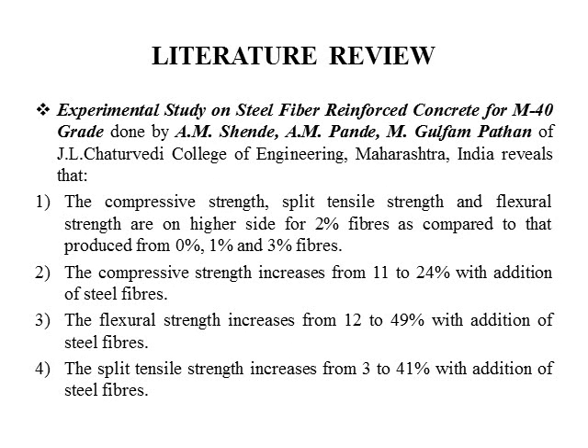Experimental study on steel fiber reinforced concrete for M40 grade concludes that the compressive strength, split tensile strength and flexural strength are on the higher side for 2% fibers as compared to those produced from 0%, 1% and 3% fibers. The compressive strength increases from 11 to 24% with addition of steel fibers. The flexural strength increases from 12 to 49% with addition of steel fibers.